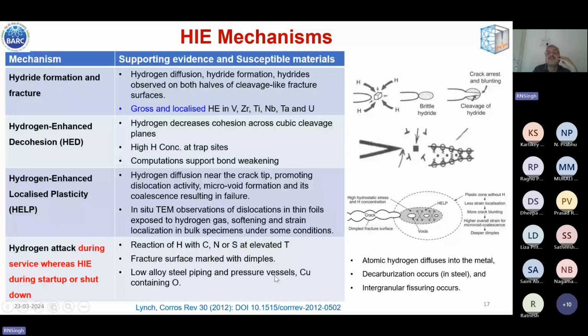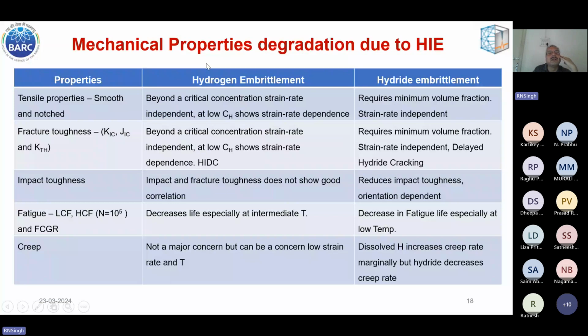So mechanical properties degrade because of hydrogen-induced embrittlement. For tensile properties, both smooth and notched tensile samples are used for evaluation. Beyond a critical concentration, it is strain rate independent. At low hydrogen concentration, it shows strain rate dependence. It requires a minimum volume fraction of the embrittling phase and is strain rate independent.